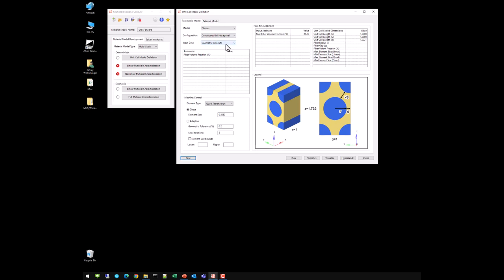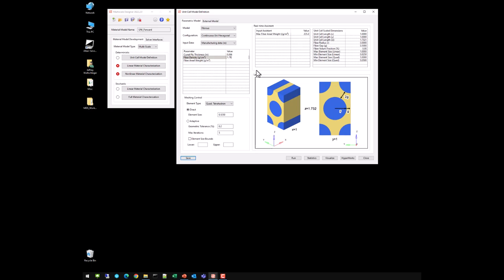We can input data as a straight volume fraction — 55% in this case — which is enough to define all the geometry. Alternatively, using manufacturing data: cure ply thickness of 0.006 inches, fiber density of 1.79 grams per centimeter cubed, and fiber areal weight of 150 grams per square meter is enough to calculate the volume fraction, which comes out to approximately 55%. We normally accept the default mesh controls, as the element size is calculated appropriate to the geometry. When you hit Run, it builds a finite element model using HyperMesh scripting behind the scenes.